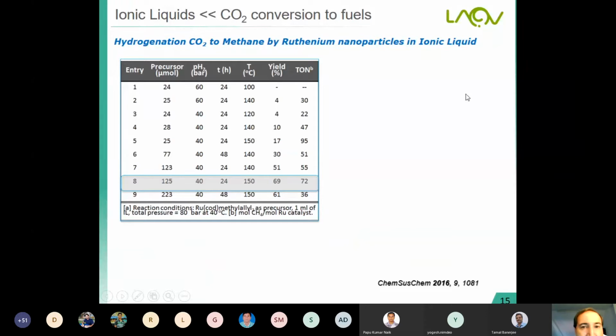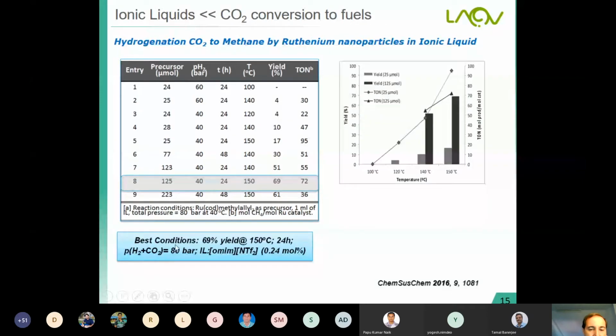We tried to optimize the reaction conditions for different points, like the quantity of precursor, the pressure of hydrogen and CO2, the reaction time, the temperature, and we obtained the best conditions using 150 degrees Celsius, 24 hours of reaction, 80 bar of pressure of hydrogen and CO2, and using a hydrophobic ionic liquid, this C8-MIM, octylmethylimidazolium bis(trifluoromethylsulfonyl)imide, only 0.24 mole %, a small quantity, and this is enough for the reaction. And we obtain 69% yield of methane.